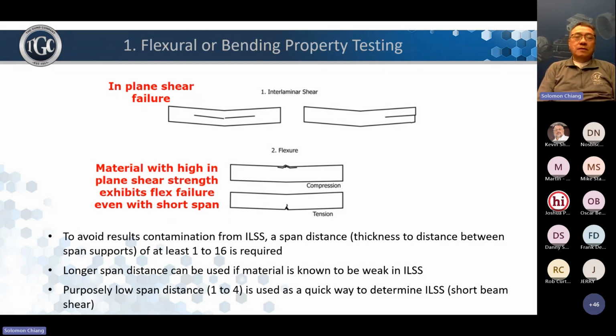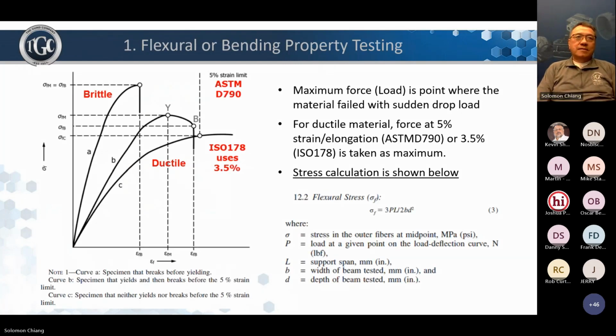And for material with weak ILSS, sometimes you need to increase the span distance beyond 16:1 to get proper flex failure data. And on a UTM, the flex test, the stress to strain curve would look like that. The bottom one, the C, is a ductile material that I showed before, and the top one is brittle. Again, with brittle, once you are beyond the linear elastic zone, the material will fail very rapidly. It would not hang in there. And ductile material would hang in there more.